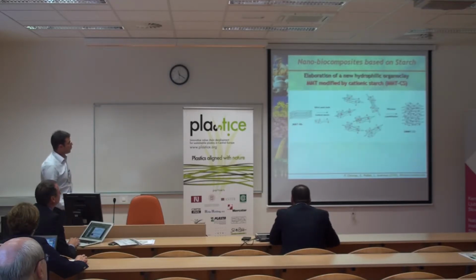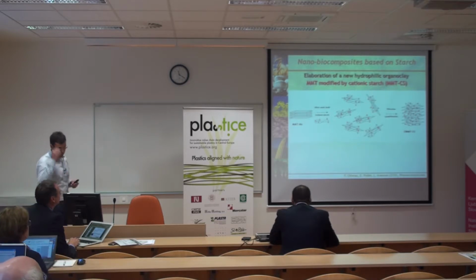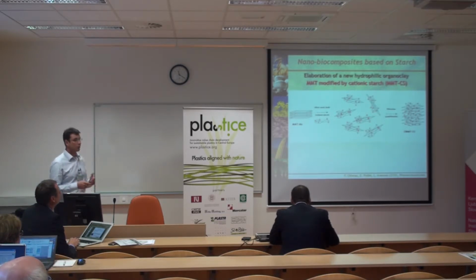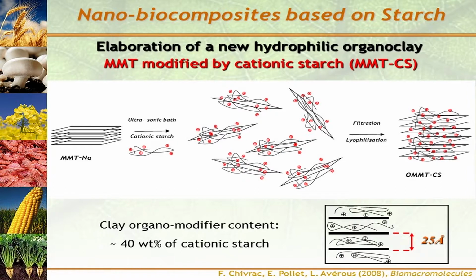So we tried and developed a new type of hydrophilic organoclay. Usually you organomodify the clay to match the hydrophilicity or hydrophobicity of your matrix. Typically, commercial organomodified clays bear ammonium salts with long alkyl chains, so you can have better compatibility with polypropylene, other polyolefins or polyesters. And here, because starch is hydrophilic, we had the idea to modify the clay using cationic starch with quite small polymer chain lengths, low molecular weights.